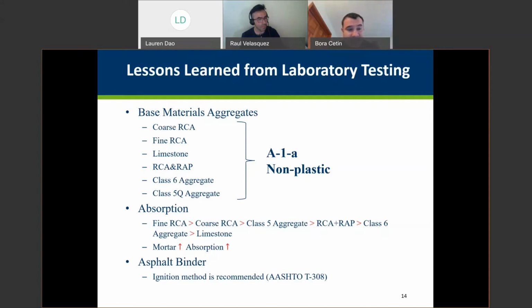And as you can see in the absorption, fine RCA had the highest absorption, and of course limestone had the lowest absorption value. And with the asphalt binder content, we will talk more about the results in our final summary slides, but there are the chemical extraction method and the ignition method. Both methods work; the extraction method provides slightly more reliable results, but it's not as fast as the ignition method. So the ignition method may be recommended if time is a constraint. Next slide, please.